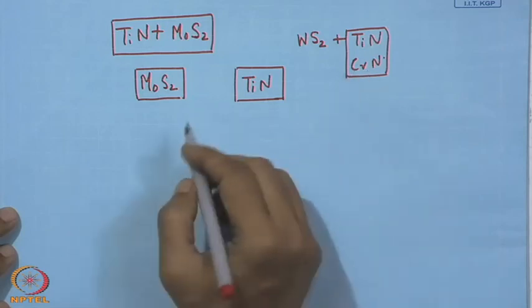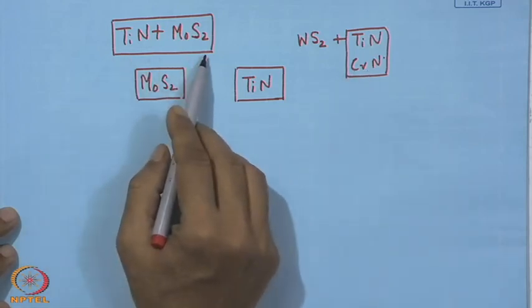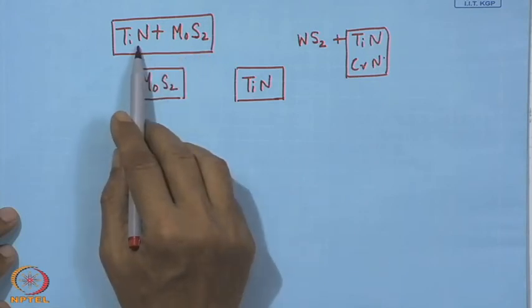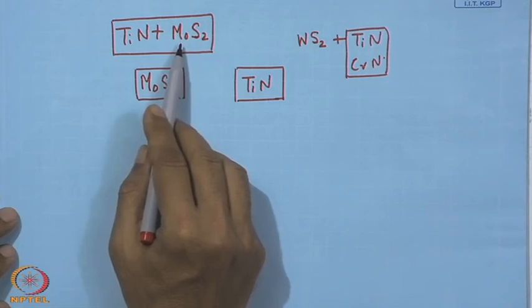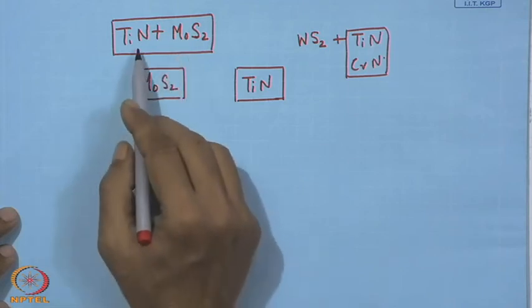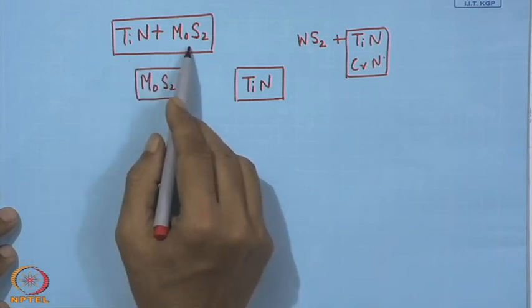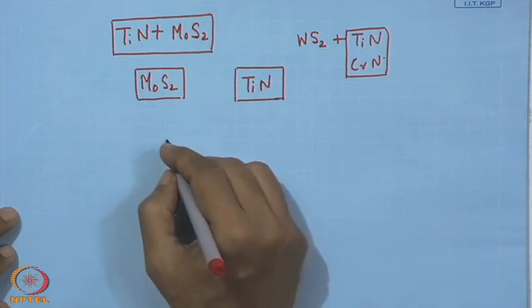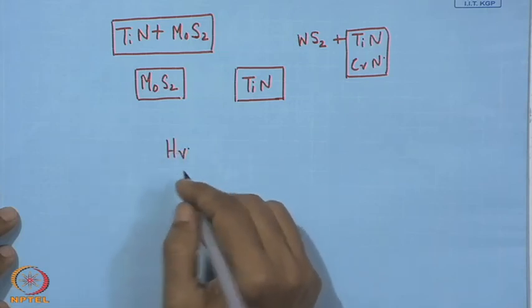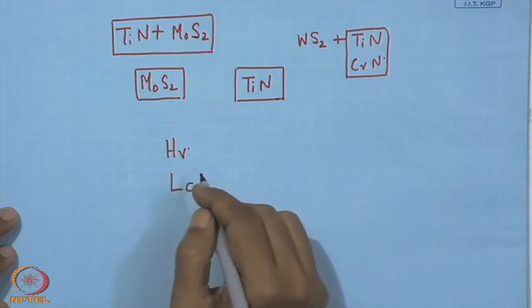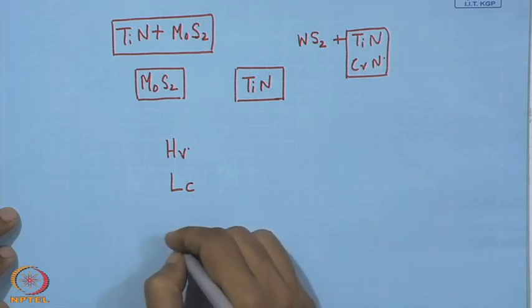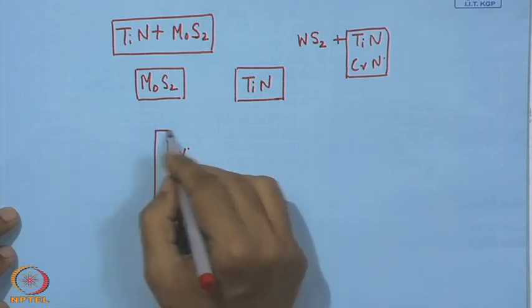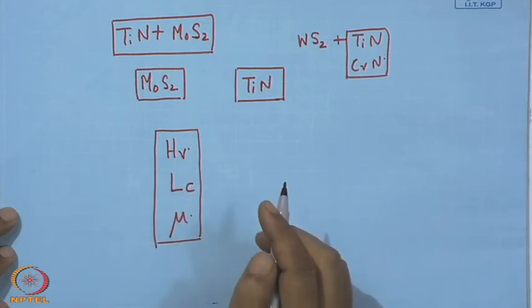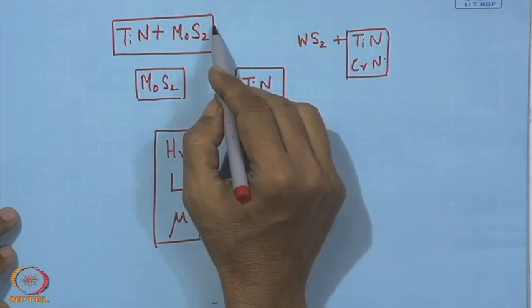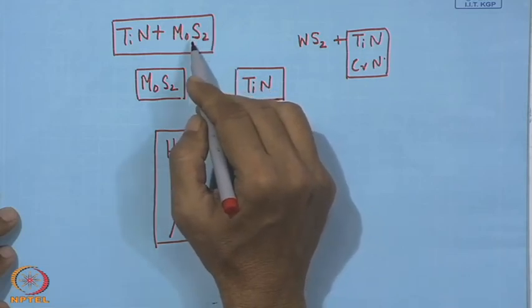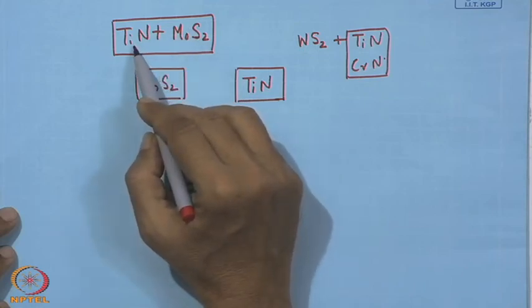That means, here comes the question of once we are resolved that it is actually titanium nitride and MoS2, that is the combination, then we have to also find out what will be the percentage of this titanium nitride and molybdenum disulfide to get the best value of hardness, best value of grain size, best value of critical load for adhesion, and also the best value of coefficient of friction. Now, for this what we need to have here actually the process parameter for depositing MoS2 and the process parameter for deposition of titanium nitride.